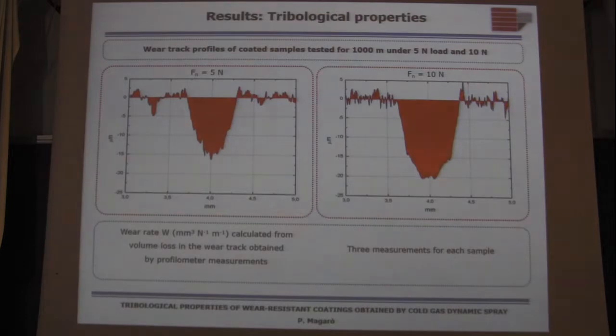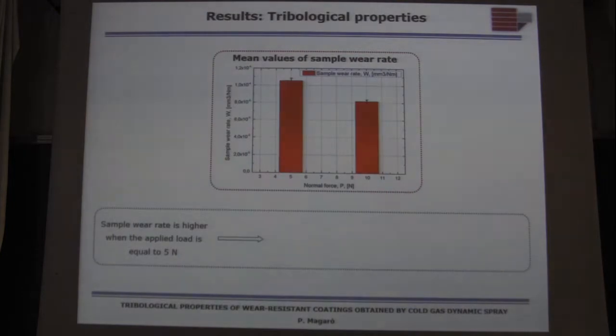So the sample wear rate was evaluated on the basis of the volume mass loss obtained by profilometer measurements, and in particular a much higher value of the sample wear rate was observed in the test in which the applied load is equal to 5 Newton. In fact, this is due to the local damage observed also before during the indentation test.